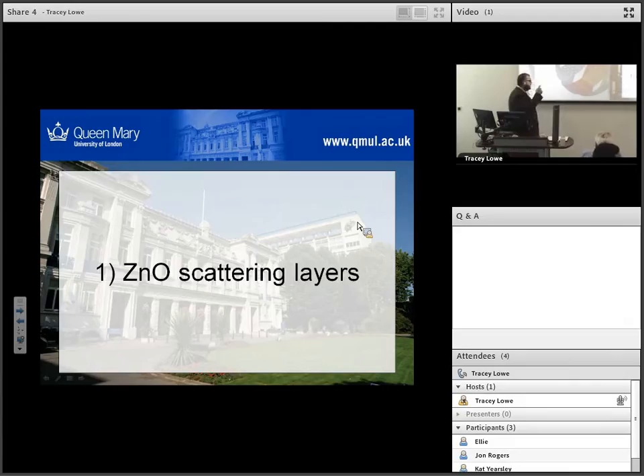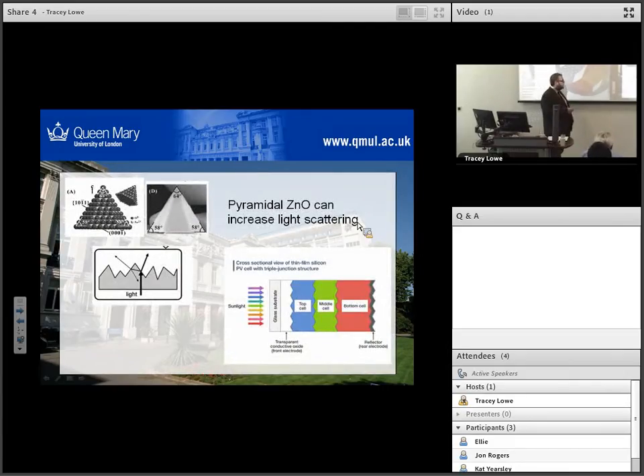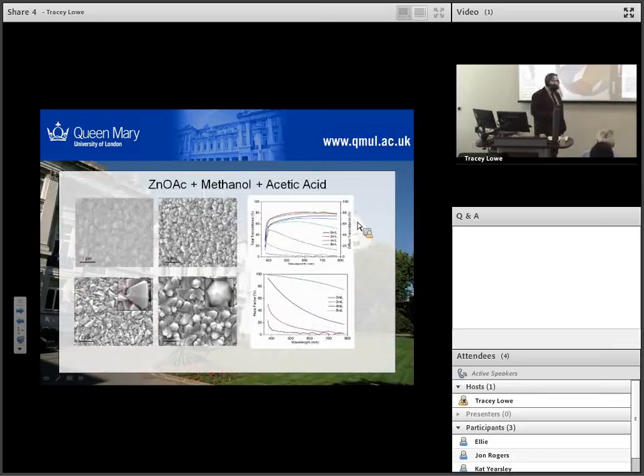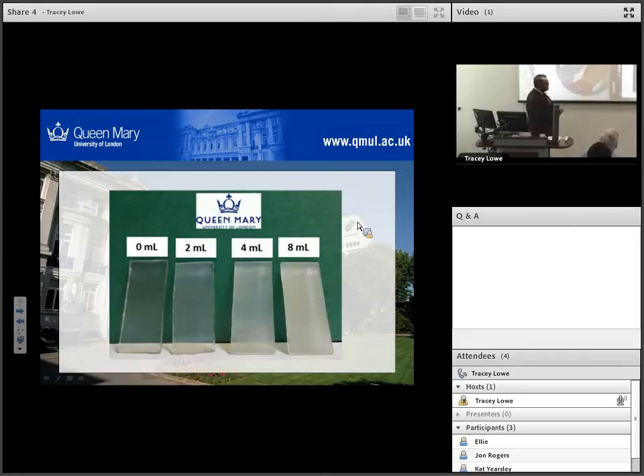First I'm going to talk about zinc oxide scattering layers. One of my students noticed that if you get this increased scattering, you'll get better uptake and improved efficiency in your solar cell. So how can we make some TCO layers which have these kinds of structures? Well, it turns out you can do it quite easily by adding acetic acid in. Increasing amounts of acetic acid into the deposition, you can get these wonderful pyramidal type zinc oxide layers. Some of the haziest films reported without using any sort of etching post-processing. So this is really nice that you can just do this in one simple step.